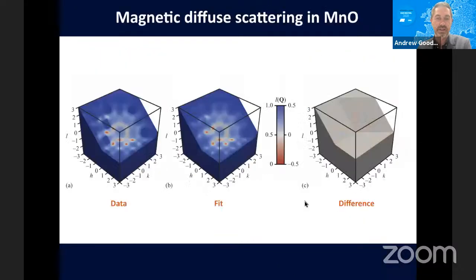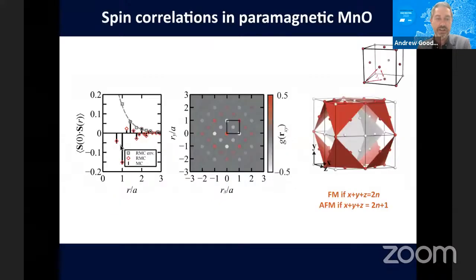But of course, because you have a sort of single crystal in your computer, you can actually also calculate the single crystal diffuse scattering. So this is often a way of recovering single crystal data from powder, but you can also fit to single crystal data independently. So for example, with MnO, you can do that. Here are Matthias's data. You can do a fit to the whole volume now of scattering data. And that gives you a model. The difference looks pretty good that you can interrogate and learn something now about the magnetic structure.